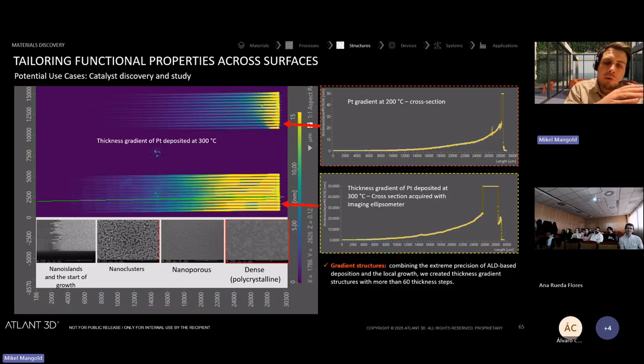This is the example of catalysis. So we were able to control the thickness, and we also control the temperature. And with different deposition, we showed that we were able to control the crystallinity of the deposition. You can see here nano island, nano cluster, and so on. So that is also something amazing. So people, in like 200 data points, you can imagine they can see which one gets the crystallinity that I want, with the properties I want for a certain catalytic activity.